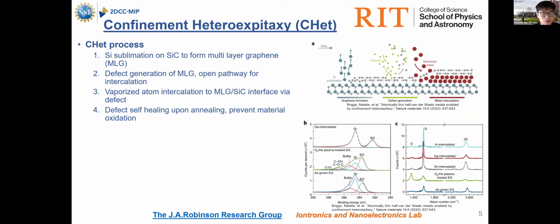That brings us the motivation to use confinement heteroepitaxy, also known as the CHet method. The general process for CHet is that first we have a silicon carbide substrate, and then we do a silicon sublimation, removing the silicon atoms and growing multilayer graphene on top of the silicon carbide. And then we do a plasma treatment to generate defects on such a substrate, which opens the pathway for atoms to integrate between the multilayer graphene and silicon carbide interface.